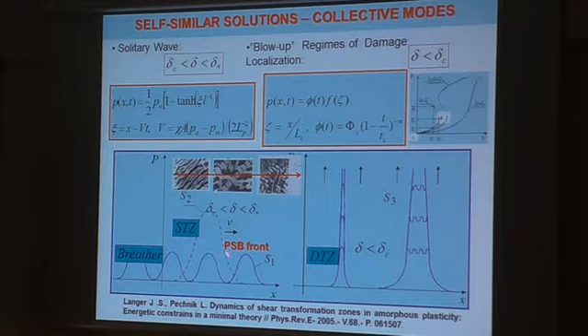Yes, because for instance this front corresponds to this transformation in dislocation substructure, and when we have final refining, when this relaxation mechanism will not appear, we will go to dislocation-free grains. And these dislocation-free grains could produce the structure with the ultimate grain refinement.